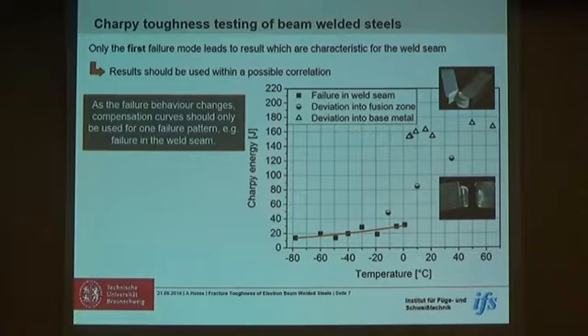As we want to connect the behavior of our beam welds, we chose only the specimen that failed with the first failure pattern, because those are the only ones that give us information about the beam, about the weld itself. And as the failure behavior changes, it is difficult to use the normal compensation curves which have a sigmoidal slope. So we use compensation curves for the specimen we chose for our correlation.